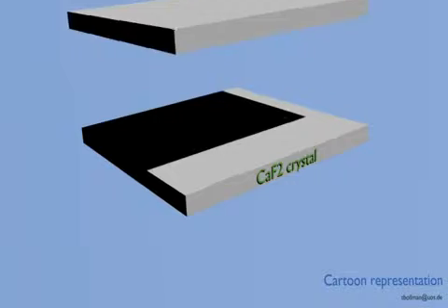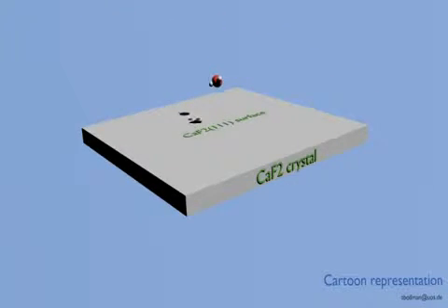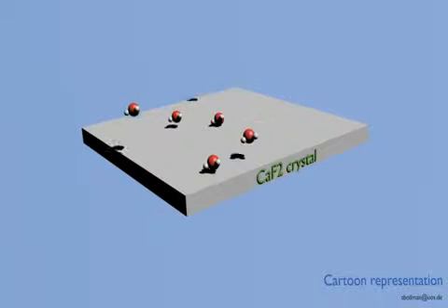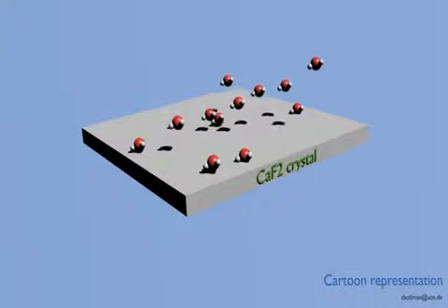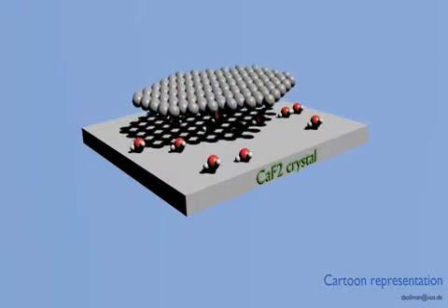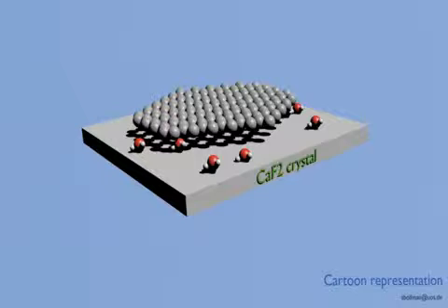To understand this water layer, we have to go back to the preparation method. As soon as we cleave hydrophilic calcium fluoride in ambient, water molecules from the ambient start adsorbing onto the calcium fluoride 111 surface. When we then exfoliate the graphene layer onto it, a submonolayer coverage of water is confined by the graphene layer. Transport of water from the calcium fluoride surface underneath the graphene results from capillary forces and explains the obtained images. Annealing results in a decay of the confined thick water film, leaving a thin hydration layer with different height levels.